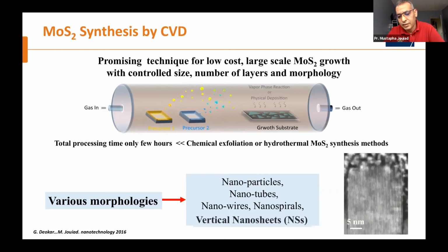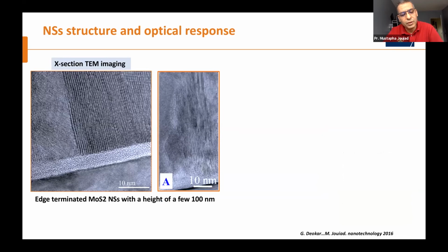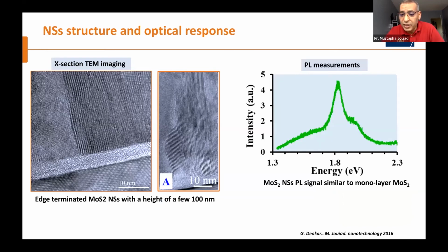This one is very interesting, and I will show you here, for example, the TEM. You have silicon, you have SiO2 as a sacrificial layer, and you have the MoS2. The first amazing result is this, for those who are not familiar with MoS2: it shows PL only when it is a monolayer, only one atom thick, a 2D material. Here with our needle-like shape, even if it is multi-layer, we are able to observe the PL, which is interesting. We can compete with very complicated MoS2 monolayers by just using this straightforward technique.